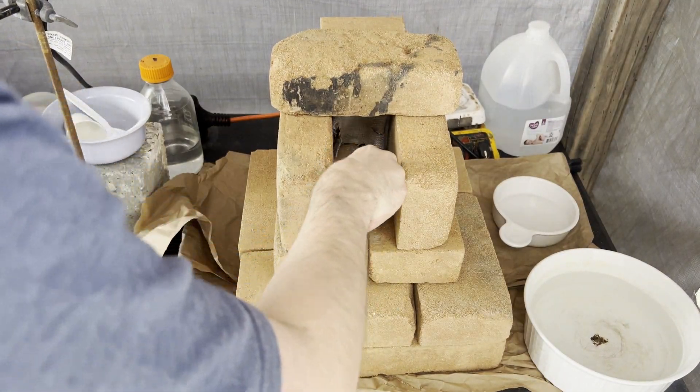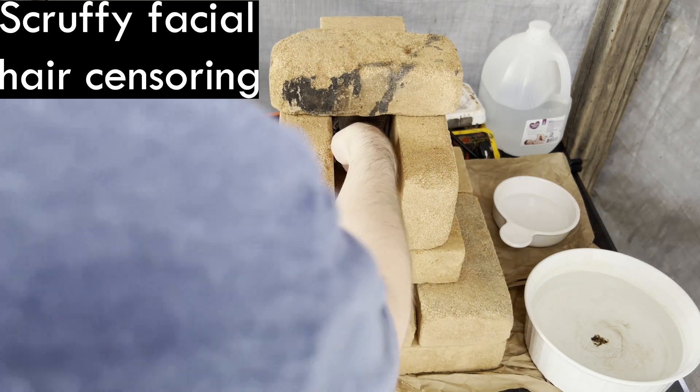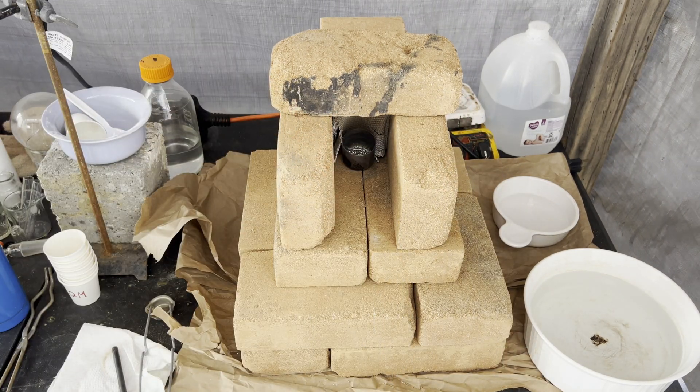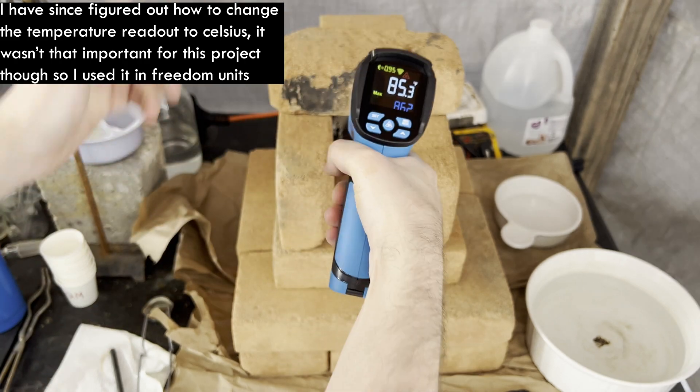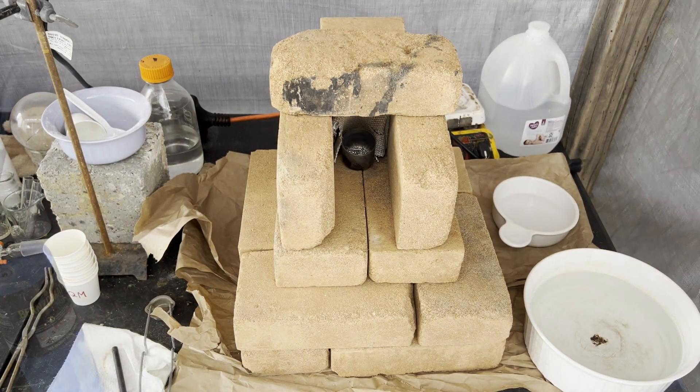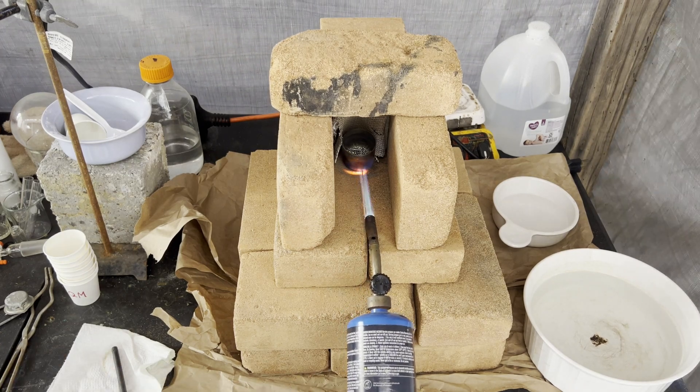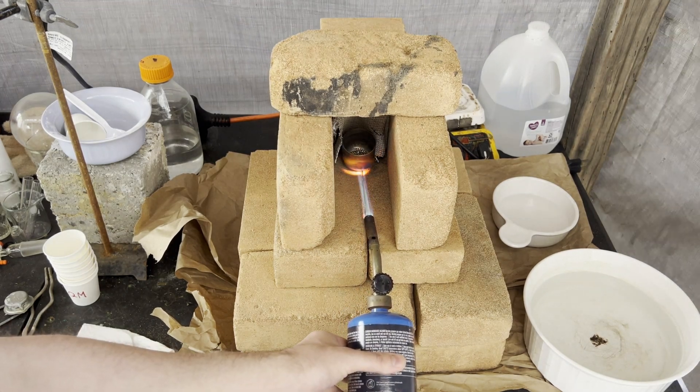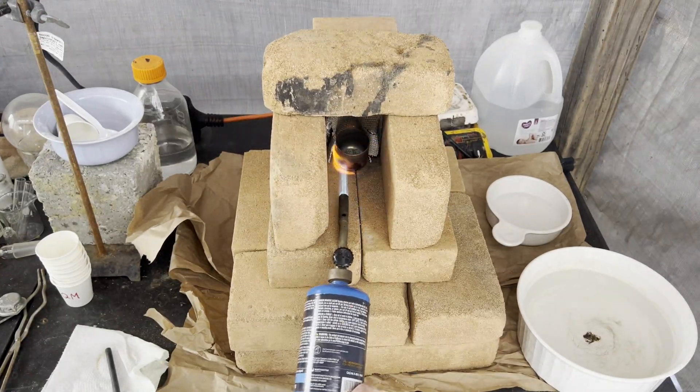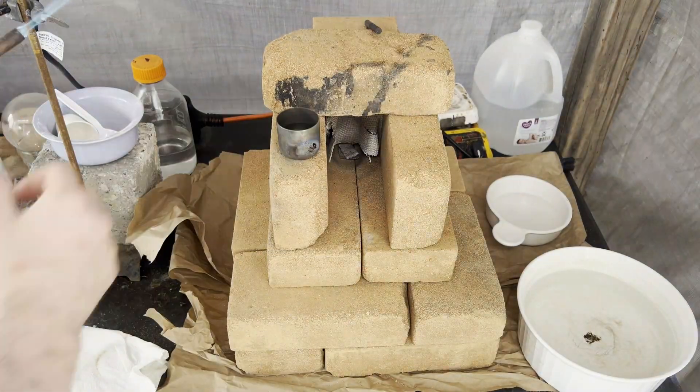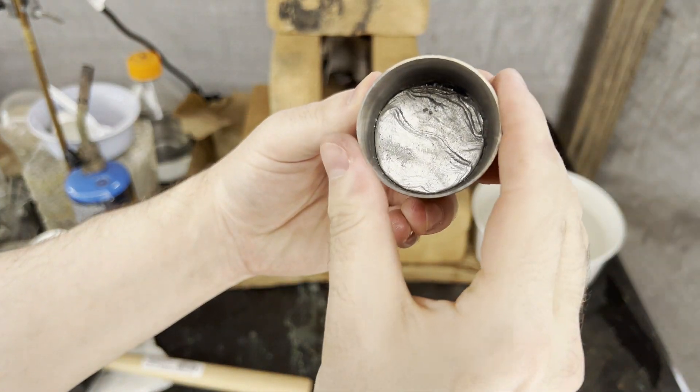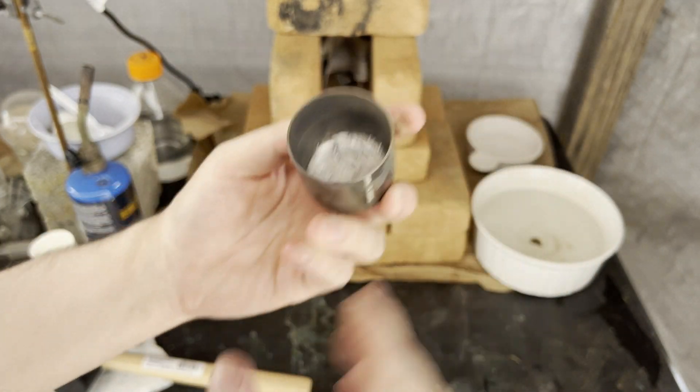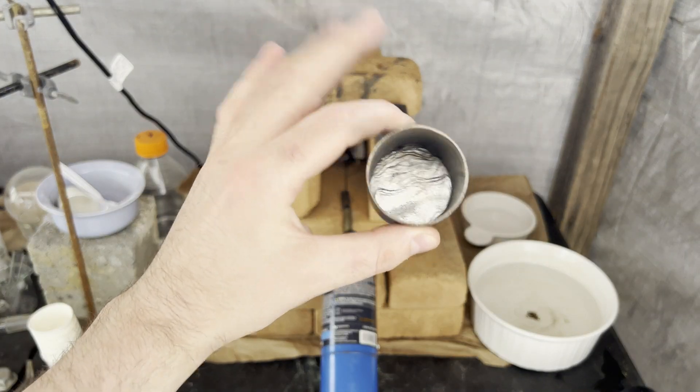The cloth in the back is made of asbestos. For the first two alloys, alloy one and alloy two, I use a nickel crucible. I didn't find much information on how readily nickel alloys with tin and/or lead, so I figured I'd try it out. Porcelain crucibles didn't work - I cracked two of them. Using the nickel crucible, you'll soon see this was a mistake as a few grams of both alloys are lost as the nickel absorbs some of the metals.